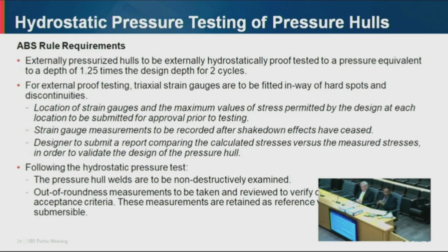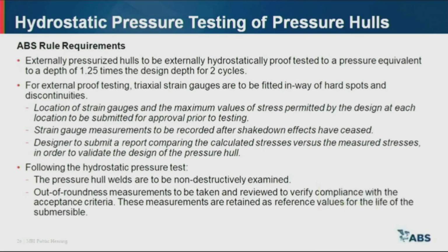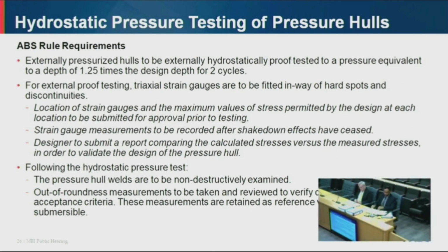So what happens if you pressure test the hull and start recording the strain gauge measurements before shakedown has ceased? You will note that the strain gauge measurements on the first and second cycles do not match. That is because shakedown is still taking place. After shakedown has ceased, you will see the readings on the strain gauge on the first and second cycle will match, okay? So typically, to verify that shakedown has ceased, you will pressure cycle the hull for a number of cycles, and then you will check the strain gauge readings. Once you confirm that the readings match, that is the point when shakedown has ceased, okay? And those are the readings you actually use for your hydrostatic pressure testing.